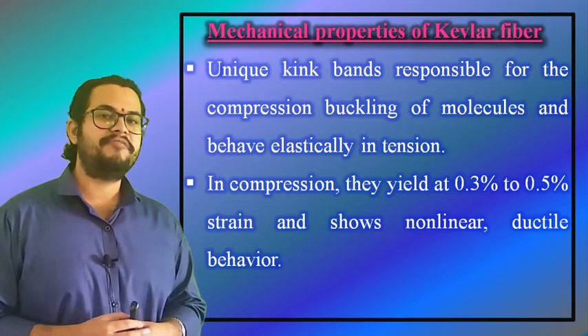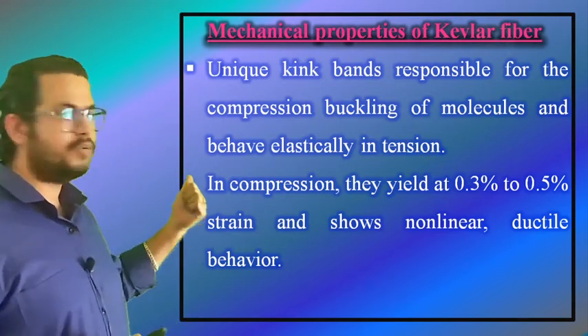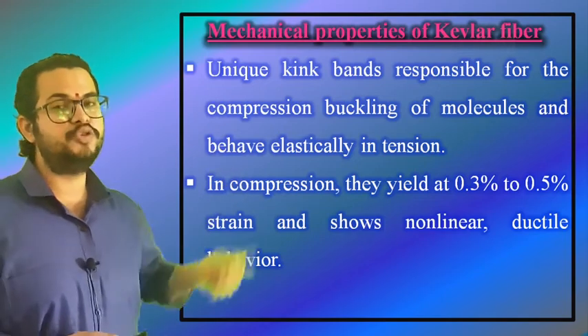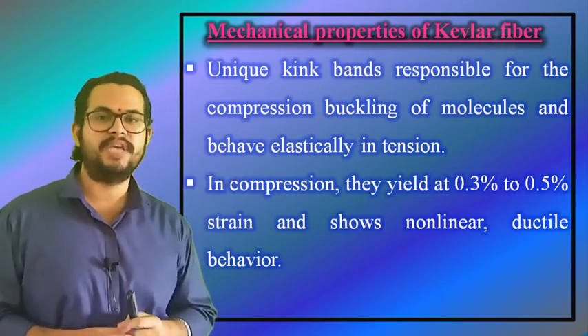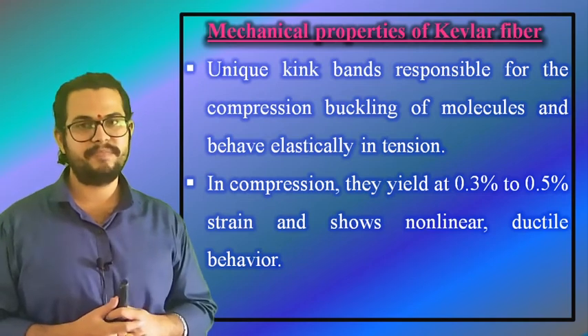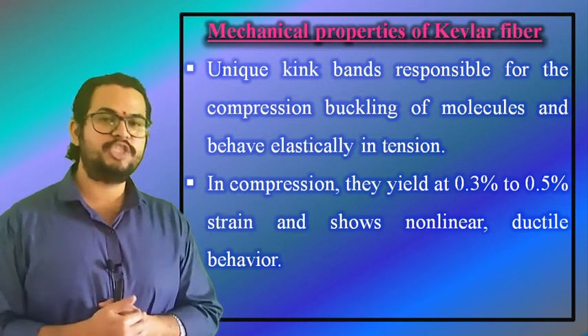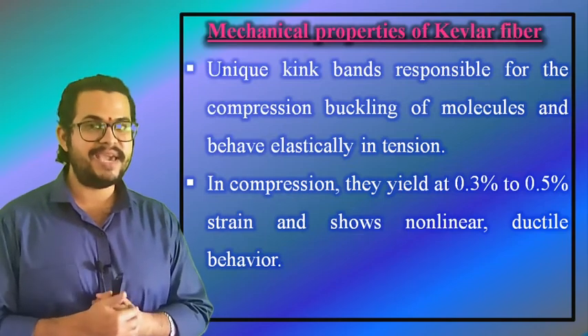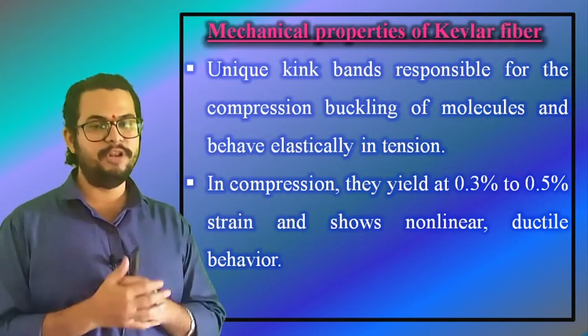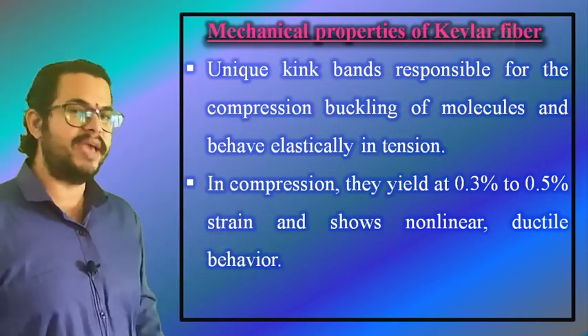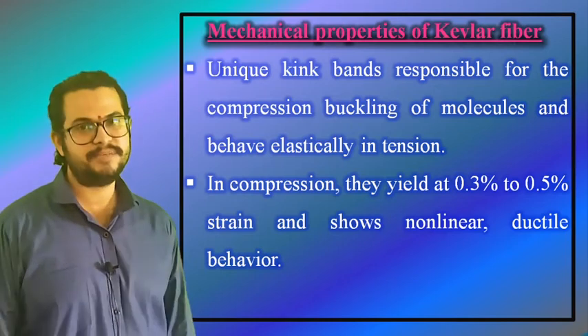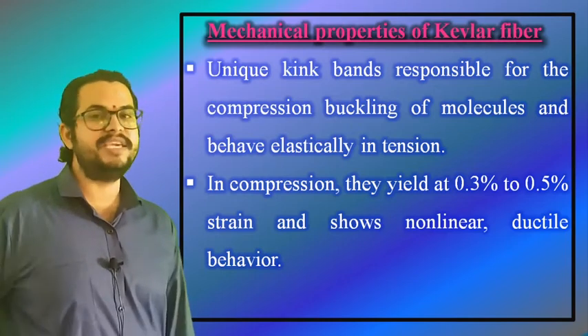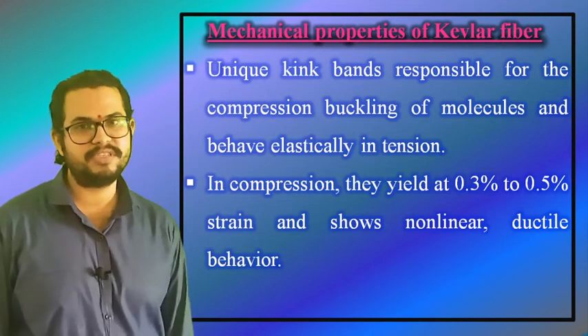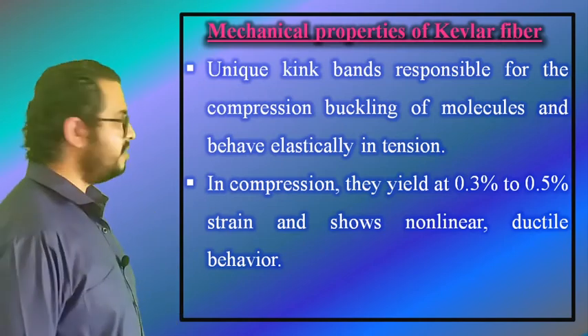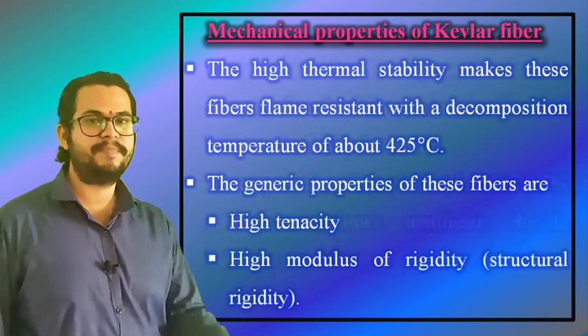The structure of Kevlar has unique kink bands. What are kink bands? They are understood to be an important mechanism in fiber failure under curvature. They form as the molecular chains within the fiber slip against each other under a compressive load, and these are responsible for the compression buckling of molecules, and hence they behave elastically under tension. In compression, they yield at 0.3% to 0.5% strain and show non-linear and ductile behavior.